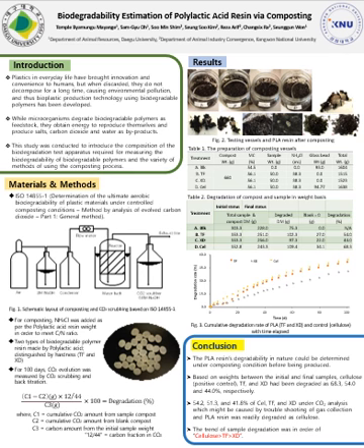Then for 100 days, CO2 evolution was measured by CO2 scrubbing and back titration. Then for the degradation percentage, we use this formula where C1 is the cumulative CO2 amount from the sample compost, C2 is from the blank compost, and C3 is the carbon amount from the initial sample weight.